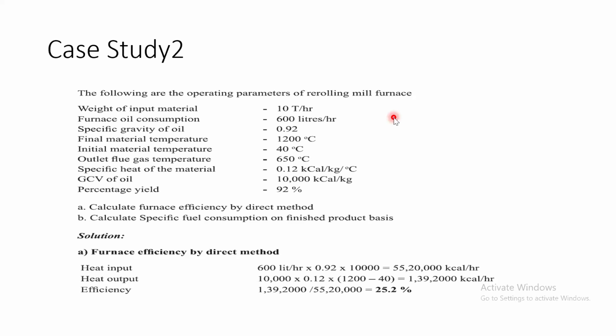Then again, 600 liters is given in liters. So ultimately, you have to convert it in kg. So ultimately, specific gravity comes into picture, which is given to us. Specific gravity of oil is 0.92. So now you can understand that the furnace oil consumption in kg per hour can be easily worked out if you multiply 600 by 0.92, so that you will get the weight of the fuel to be heated in kg. So furnace oil consumption in kg is 600 into 0.92.